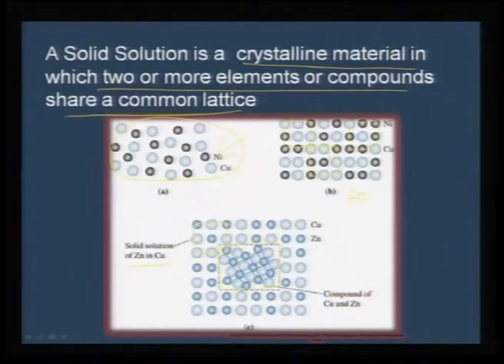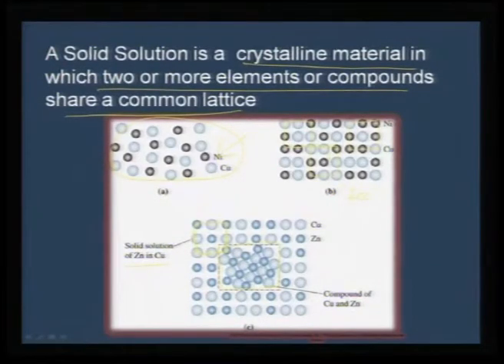But along with that, there is also a region where it is not a solid solution, but some compound of copper and zinc is precipitating out, which means there is a restriction. I cannot go beyond a particular solubility limit where I can retain the FCC structure of copper. In other words, it is lost. Therefore, you get a mixed phase there and you do not call that a solid solution. So, solid solution in this case is only up to a maximum amount, not like the nickel copper case where throughout the entire compositional range, they exist only in FCC. But in this case, there is a problem because zinc has a different crystal structure compared to copper.